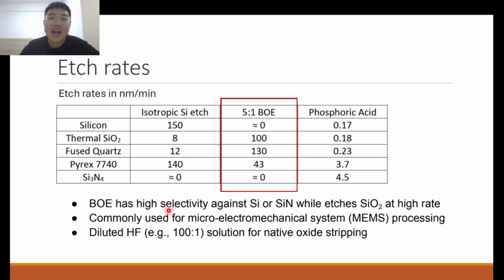Okay, so let's take a look at etch rates to find out the selectivity of this kind of oxide etch. It turns out that this buffered oxide etch etches your thermal SiO2 and your quartz, both silicon dioxide, at a very fast rate, but silicon and nitride are close to not etched. So we can see that this buffered oxide etch has an extremely good selectivity for SiO2 over silicon. If you see something like Pyrex, it also contains some SiO2 species, so there's somewhat of an etching of it.